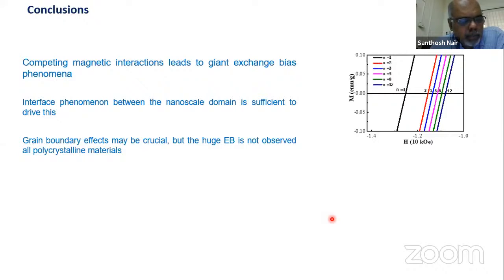But a recent paper by one of the groups, making a single crystal of a simple perovskite, showed that the exchange bias is not there, pointing at the fact that grain boundary effects are very important. But we believe that grain boundary effects alone are not enough to give exchange bias, because our lanthanum, strontium, iron, cobalt system doesn't show any exchange bias in a polycrystalline sample. So it's an interesting area, still a lot to be explored. I think I will stop at that. I'll be happy to answer any questions.